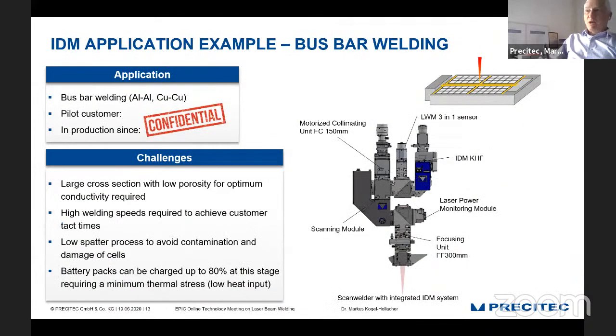So again, busbar welding, again, the scan welder of Precitec in combination with the OCT sensor, and a device which we called keyhole finder. This is a new device which comes with the OCT system to align the sensor spot, the measuring spot. You have to be aware of the fact that we are talking about a diameter of the measuring beam of about 50 to 70 micrometer. And the alignment of that measuring beam is very, very important. That's why we need some devices to help the customer to align that measuring beam to the right position.